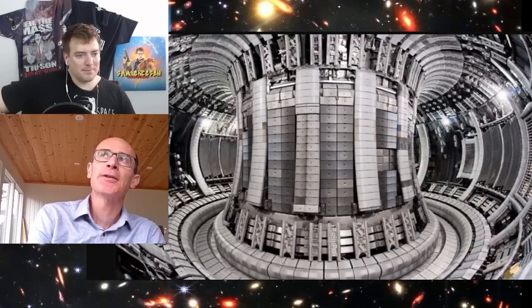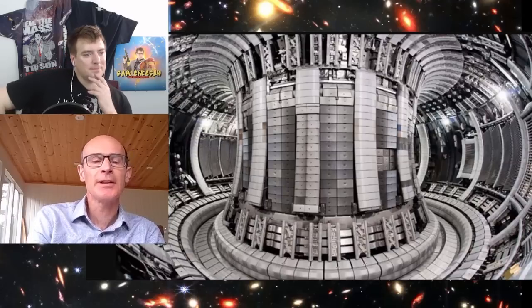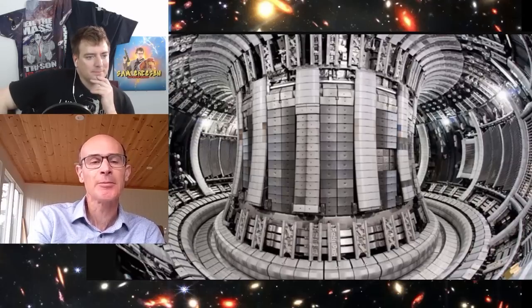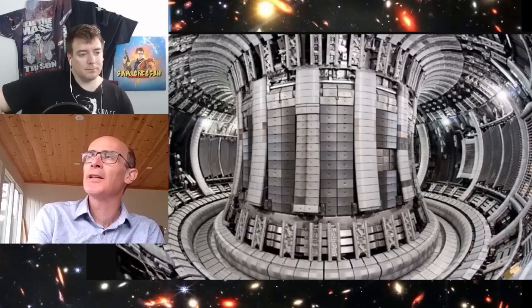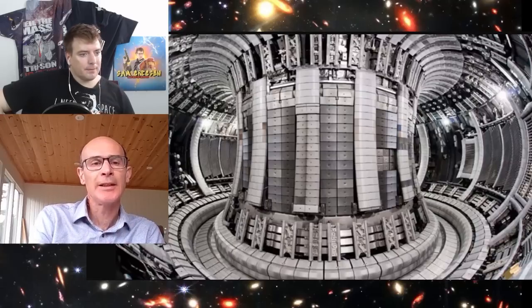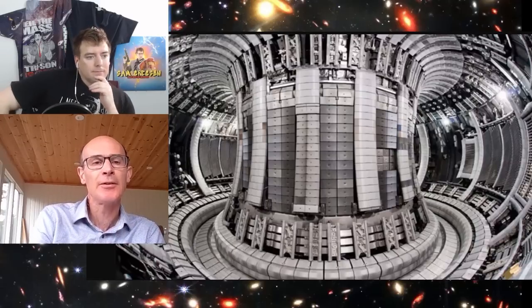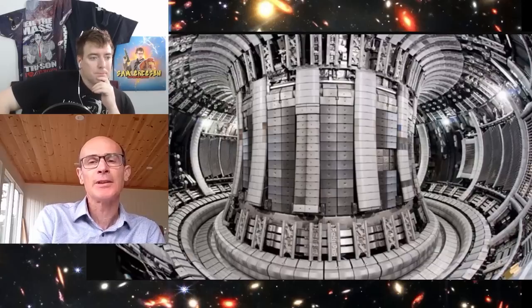So there's also a general correlation between the size of the current, the maximum current that a superconductor can carry, and the maximum magnetic field that it can withstand before it goes into the normal metallic state. Those generally correlate with the superconducting transition temperature, the TC. So that's one of the reasons why a higher TC superconductor would be useful, because even if you operated it at low temperatures, it would allow you to carry, generally speaking, a larger current than lower temperature superconductors.